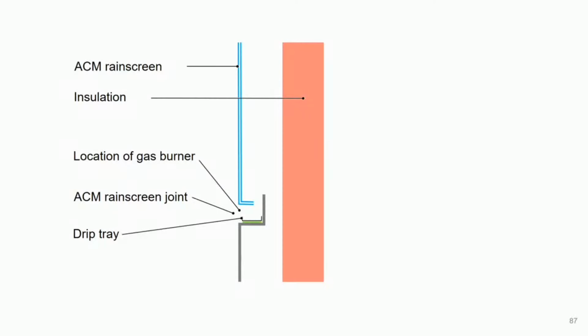I placed a small drip tray, shown here, on the ledge under the burner. This would allow me to collect dripping polyethylene in a consistent way between each of the experiments and to ensure experimental repeatability. Because I was interested in these experiments in escalation of the fire upwards, the lower part of the rain screen was fabricated in solid steel, that's the steel shelf shown here, rather than in ACM.